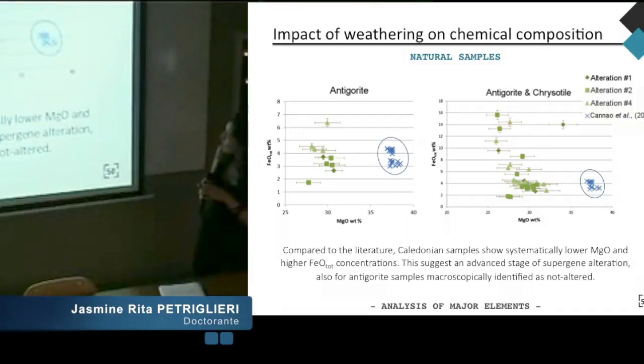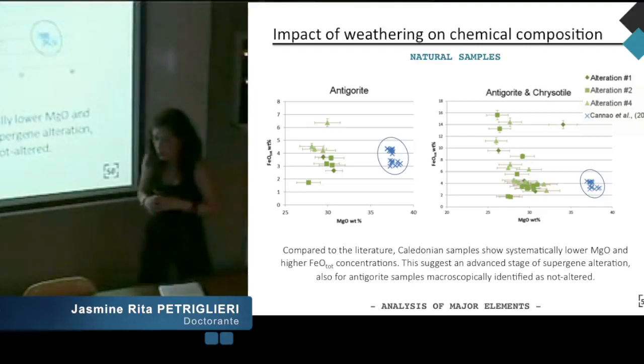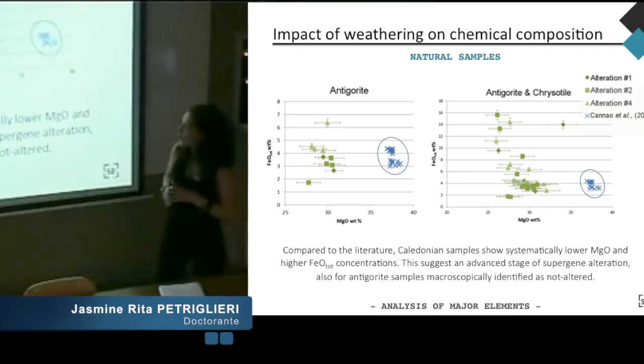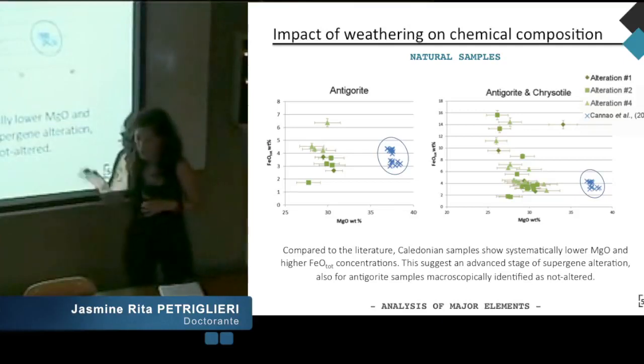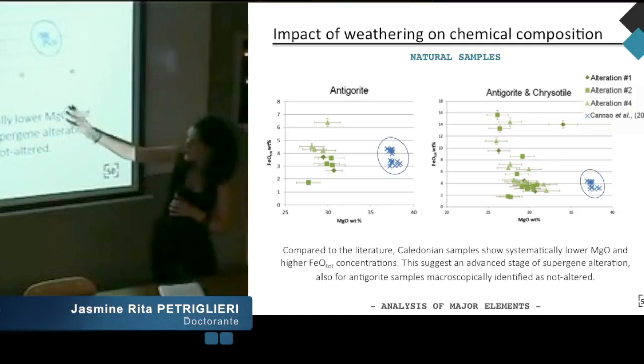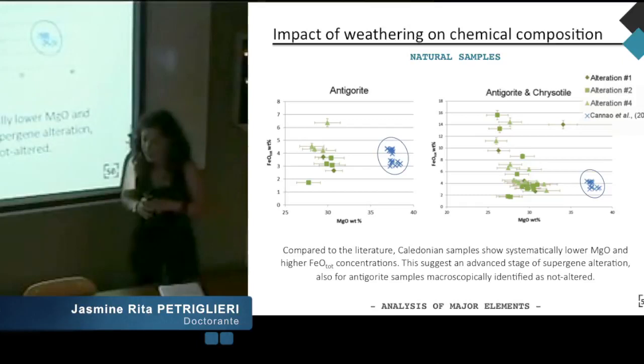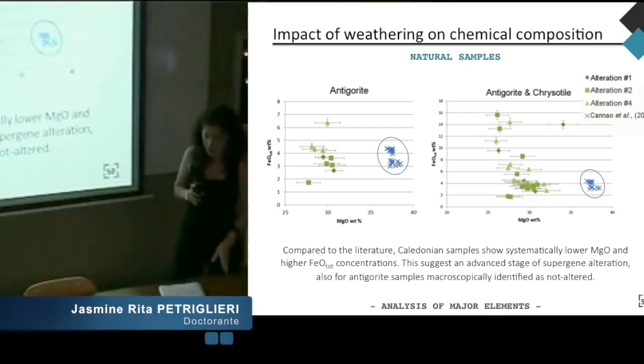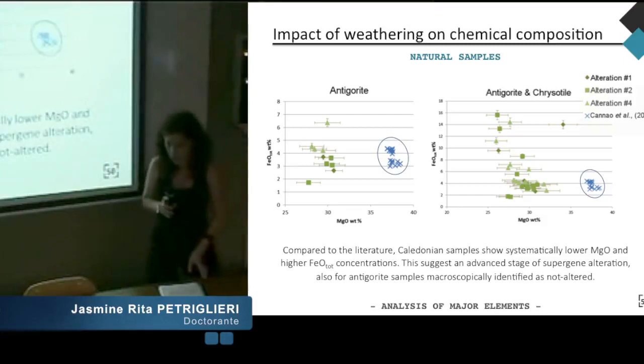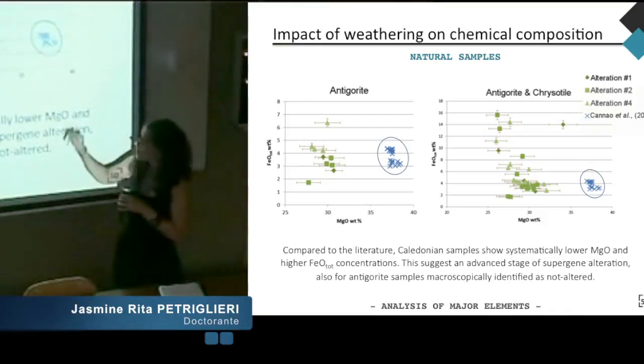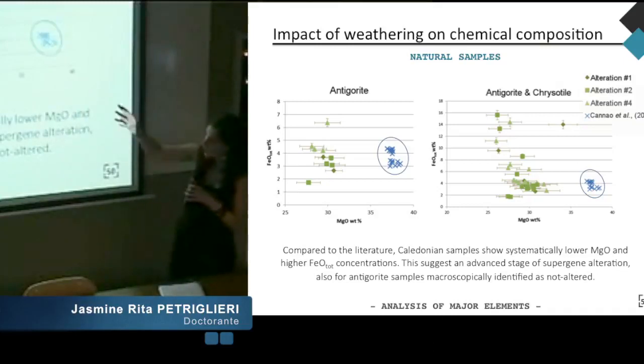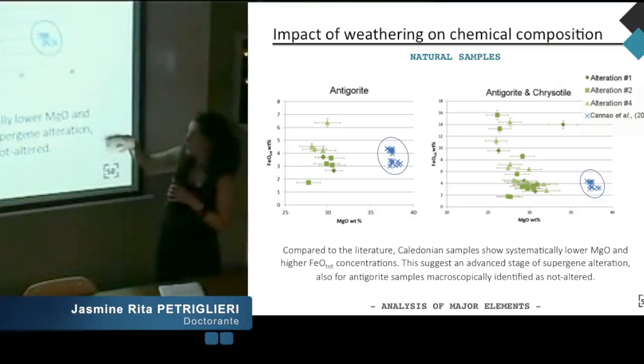To test the weathering on chemical composition, analysis of major and minor elements of natural samples was carried out, and here I report the data acquired for antigorite and antigorite-chrysotile samples for magnesium and iron content. Compared to the data of literature that are circled in blue, Caledonian samples show systematically a lower magnesium content and a higher iron concentration. This suggests an advanced stage of the supergene alteration also for antigorite samples that macroscopically were identified as not altered. All our samples probably are already altered. And in addition, for antigorite samples, we can observe an increase of iron content correlated with the increase of the state of alteration.